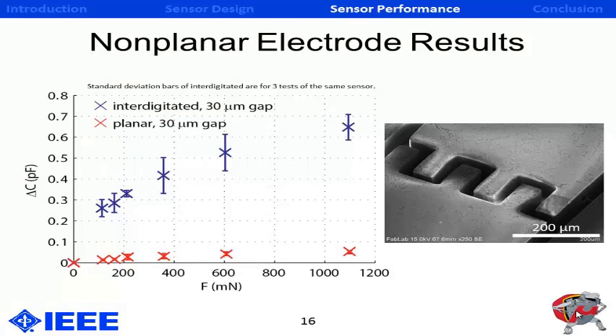Lastly, a non-planar electrode was fabricated and tested, and it was found to have about an order of magnitude higher sensitivity than a corresponding planar electrode. So the premise was, although we couldn't necessarily analytically model it, we assumed that a higher surface area in between the electrodes would net a higher sensitivity.